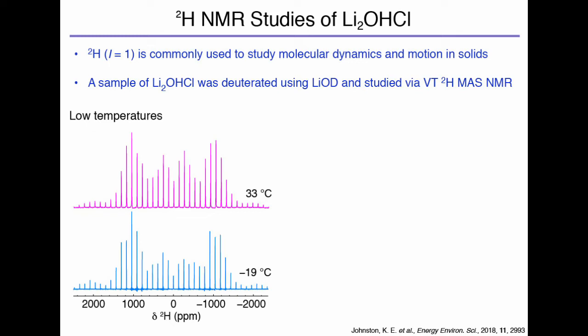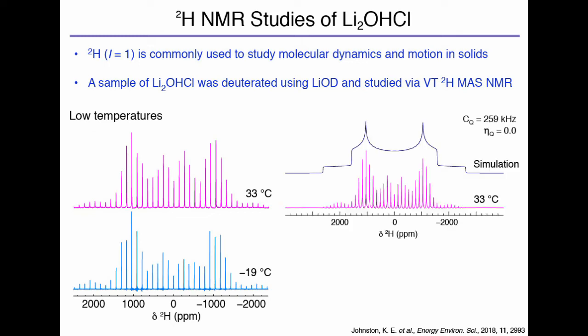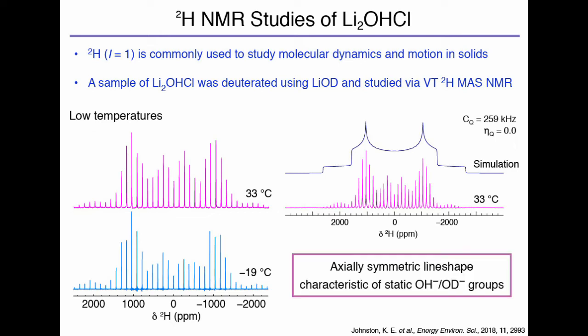But the main point here is that the spectrum that we see at minus 19 and at 33 degrees C are identical. And what we can do is simulate that and extract some parameters. And essentially, what this is telling us in terms of NMR is that those protons are static. They're not moving at minus 19 or 33 degrees C, which is good. That's in agreement with our previous data.